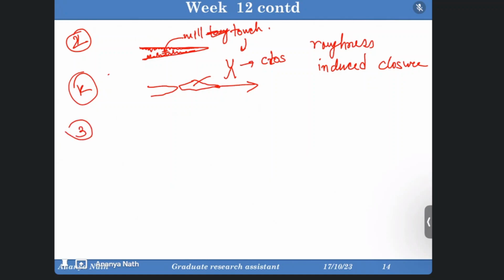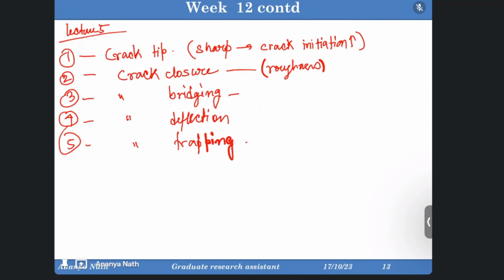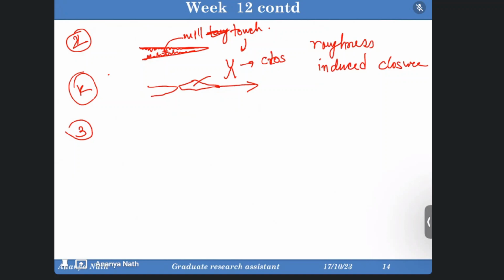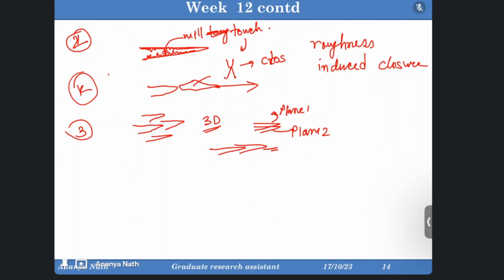Then the third thing is this crack bridging. First of all, crack bridging means two cracks are getting bridged. So it's like if there is one crack, if there is another crack. I am drawing this in 2D, but you imagine it in 3D. If there is one crack and there is another crack which is in the upper plane. So if it's on plane 1 and if this is on plane 2, okay, these are micro level or nano level cracks, and if this propagates, one thing may happen due to the propagation, all the cracks are gathered at one position now, and all the cracks are getting bridged over one another. So the cracks are making some stack over there, some stack of cracks, and due to this stacking it will be called as bridging.